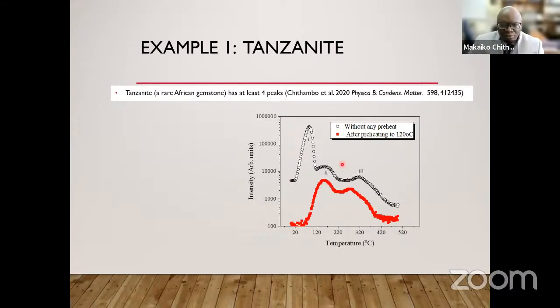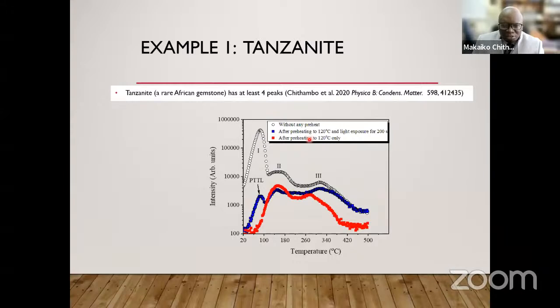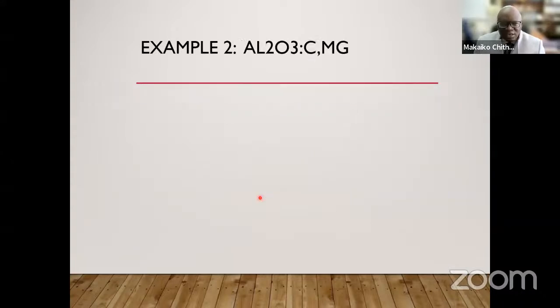This graph compares a glow curve measured without any preheating, which is the first one here, and then the one in red, measured after preheating. Once you've preheated your sample, you can see that you've removed peak 1. Then in the third stage of the process, you expose the sample to light and measure your glow curve again. This one in blue is measured after exposing the sample to light, and we can see that peak 1 is regenerated. So this is your phototransfer. In other words, the electrons responsible for that emission have been transferred from some deeper electron trap to this shallower electron trap. Here's another example of aluminum oxide doped with carbon and magnesium.